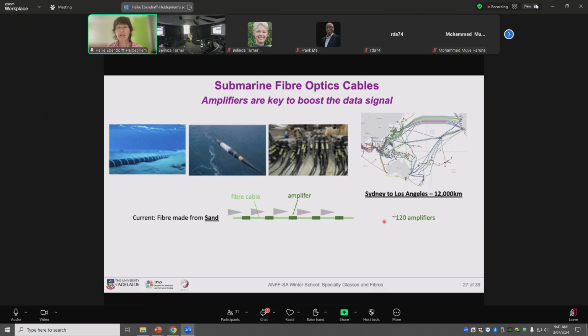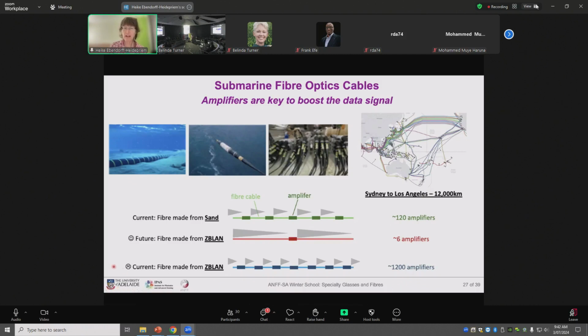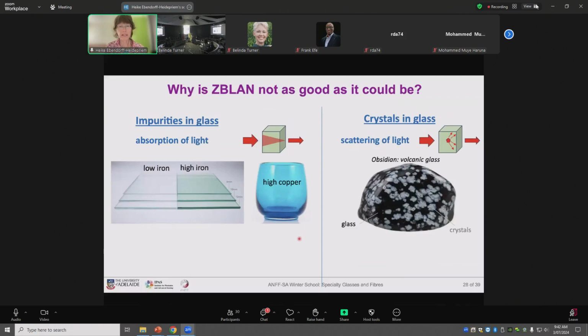So there's really a driver to have fewer amplifiers so that we can have more signals going into one fiber. And theoretically, the so-called ZBLAN fiber allows us to do this because theoretically it has a lower loss. What it means is the light only decreases over 2,000 kilometers to such an extent that only then an amplifier is needed. So theoretically, we would only need 6 amplifiers from Sydney to Los Angeles. Huge improvement. So very happy. Theoretically. Practically, it's the other way around. Current ZBLAN fibers, their loss is even worse than that of the current fiber optic cables made of silica, so we would need more amplifiers. So we need to do something so that the ZBLAN can achieve what it is theoretically able to achieve.